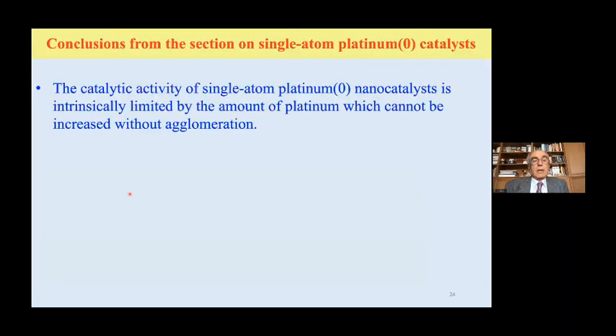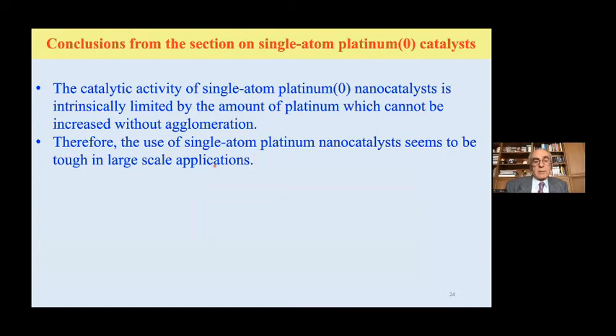But there is another problem. The catalytic activity of single atom platinum nanocatalysts is intrinsically limited by the amount of platinum, which cannot be increased without agglomeration. When we increase the platinum amount or content, the platinum atoms will be close to each other and they can agglomerate very easily. They can interact with each other. And therefore, the use of single atom platinum nanocatalysts seems to be tough in large scale application.